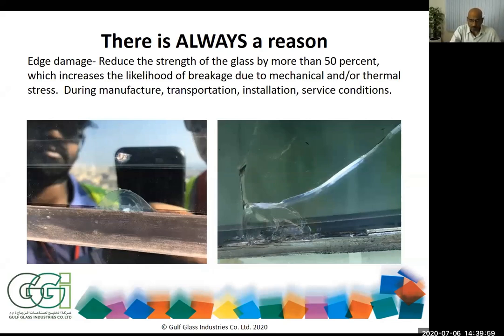So this job was nearly 20,000 square meters of heat strengthened glass, and we had a lot of breakages on the heat strengthened glasses. But the inner one, tempered glass, which was another 20,000 square meters, we did not have any spontaneous breakage on this building. So that shows us that edge damage is one of the key reasons where we can find breakages.